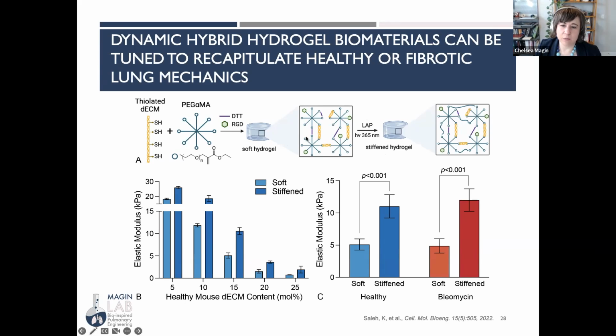So that means that we leave some of these alpha methacrylate groups open, and then later we can react them to stiffen the hydrogel. So in that way, we can create healthy soft hydrogels, healthy stiff hydrogels, which don't exist in vivo, diseased or fibrotic soft hydrogels, which again don't exist inside a mouse model, and stiffened fibrotic hydrogels. So now we can decouple the biochemical changes in the lung from the mechanical changes in the lung and start to understand which one of these is a bigger driver of fibrotic disease progression.